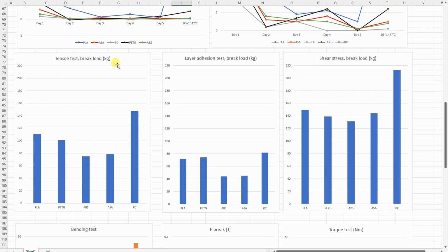Then let's say the tensile test, the layer adhesion test, and shear stress. And you can see the scale is equal, 220 kilograms max. And the polycarbonate was the strongest in the tensile test, and very impressive. Look at these values. On the layer adhesion test, even the ABS and ASA at 40-something kilograms is also very good, but this was really impressive, 81 kilograms on layer adhesion on polycarbonate. The shear stress is very similar, but again the polycarbonate showed the best properties here.